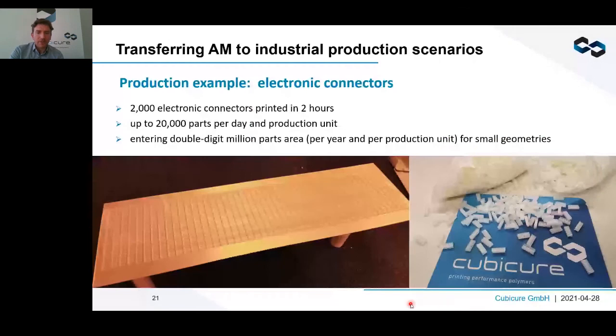I'll give you two more examples of this productivity, and then I think I've consumed my time. So the first thing is, as you can see here, a full printing platform, a 1 meter long printing platform with small electronic parts. You see the parts on the right side. These are very small connectors. I think they're 16 pin connectors, and you can print like 2,000 of them in only 2 hours. So that means with a single production unit, we are already entering the tens of thousands, 20,000 parts per day regime, which ends up in the millions, even double-digit millions of parts for small parts, with single production units. So we are really entering the mass production field with AM technologies, something which was unthinkable a few years ago, but this is really happening now.